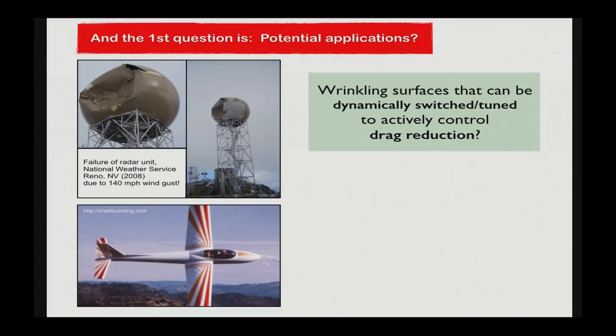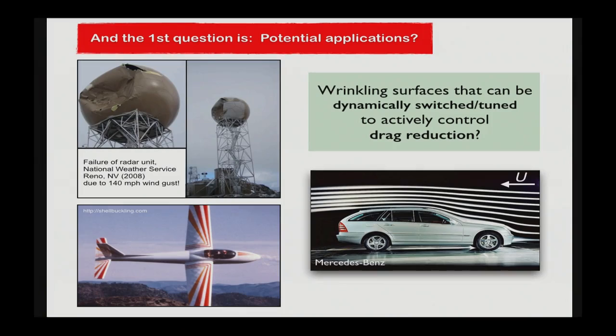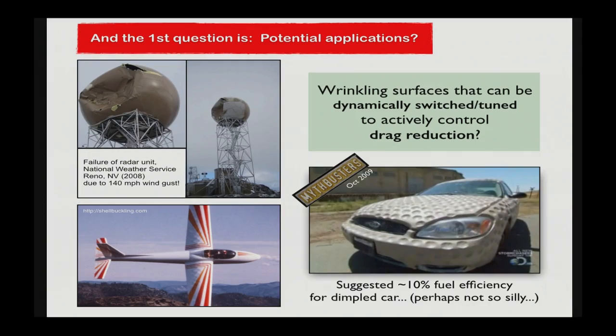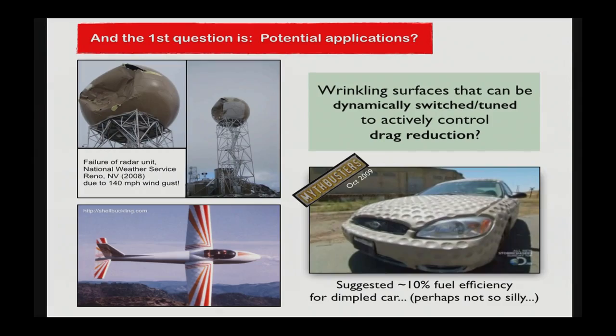We might think about affecting the boundary layer next to the wing, the airfoil of an airplane, perhaps to change drag and lift. An even more concrete application is perhaps to play with a region where the flow separates from a car, and we might be able to reduce drag in these structures, therefore increasing fuel efficiency. In fact, this sounds silly, but Mythbusters, which is very serious, actually went and checked this out. They cast a car with all these dimples, and they were able to show that they could increase fuel efficiency by about 10%. However, they had no way of knowing what dimple size to optimize for and so on. I think with our design tool, we might be able to get there.